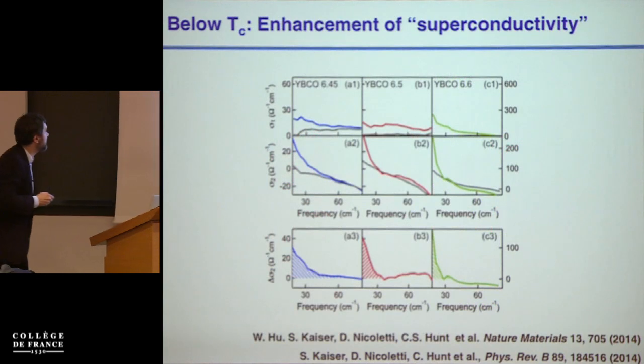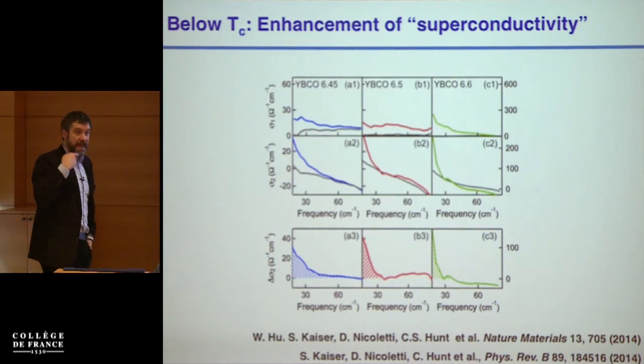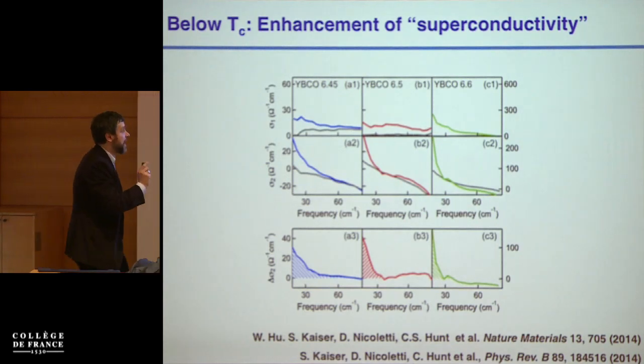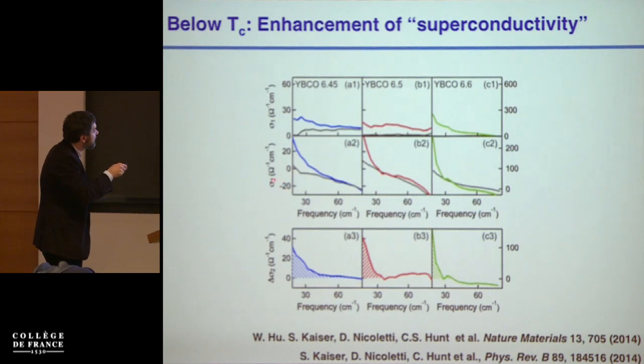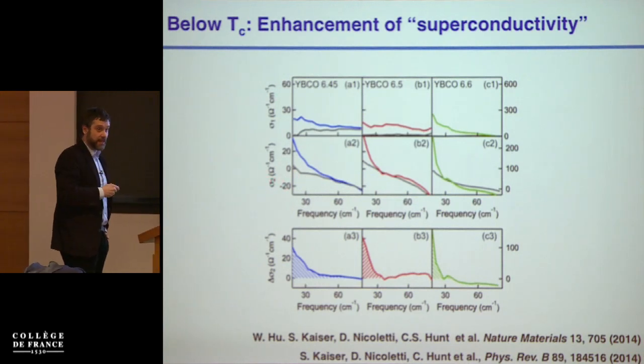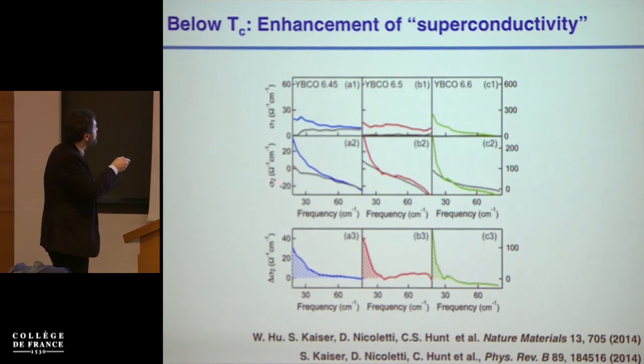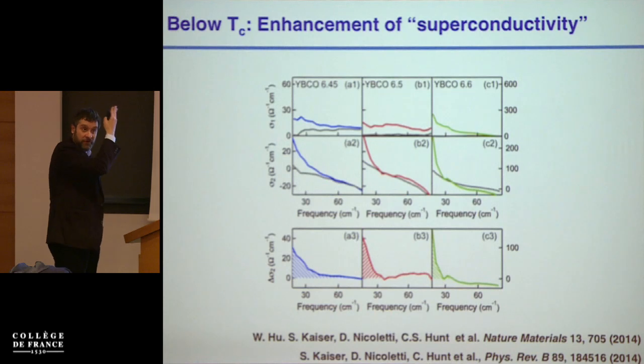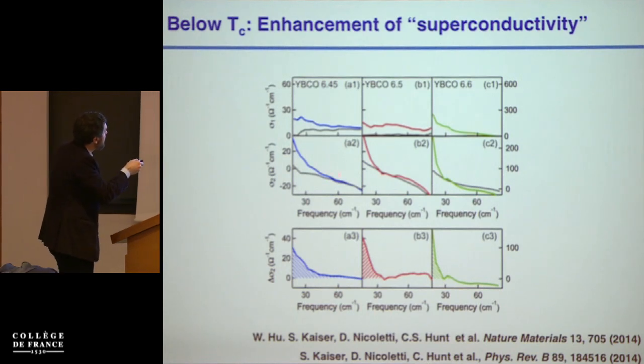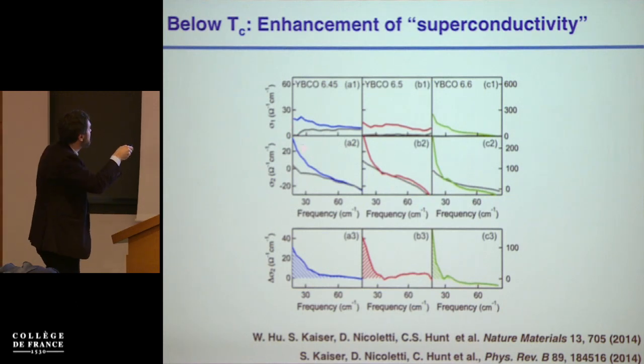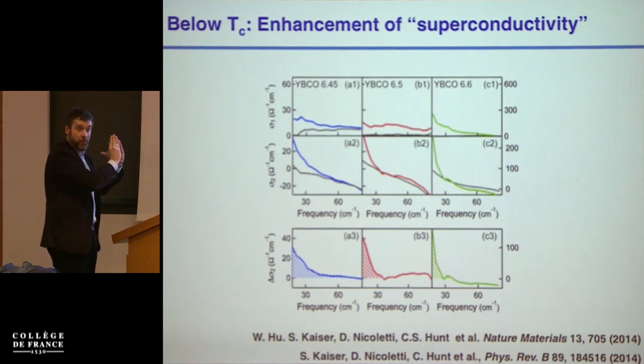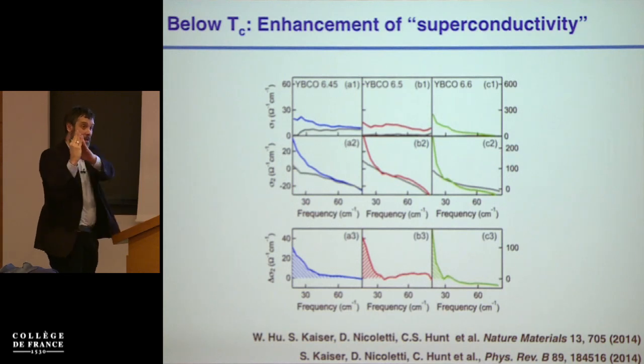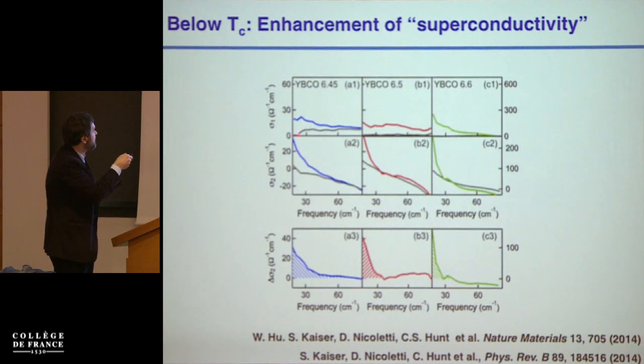This is actually clarified better if I plot now the optical conductivity, which is something I've discussed in the last lecture. What you really want to look at when you think about the strength of superconducting coupling is the way the inductive conductivity looks like. According to the London equations, or just the basic superconducting equations, sigma 2 in a superconducting state is supposed to diverge at low frequencies like 1/omega and become infinity at zero frequency, where the Meissner effect is found. And the way this sigma 2 is diverging is indicative of how strong the superconducting state is. Or, in other words, the way this diverges is related also to the spectral weight in the delta function of sigma 1 and the position of the plasma edge. Okay, so a plasma edge shifted to the blue means that this thing diverges stronger.